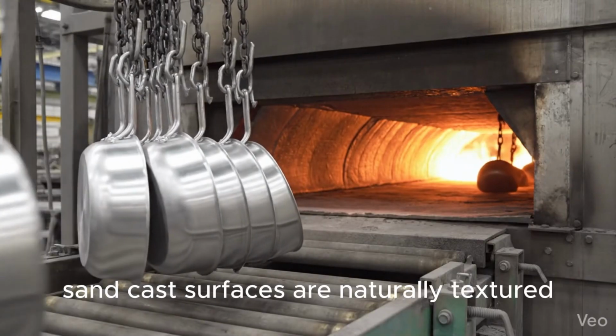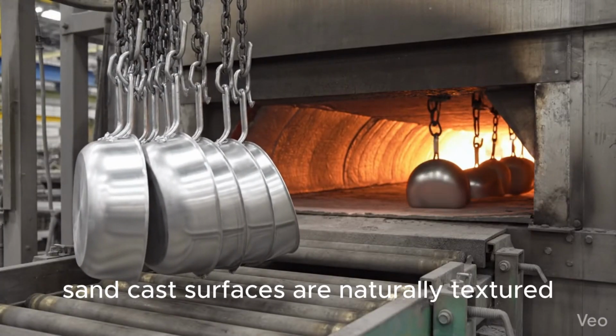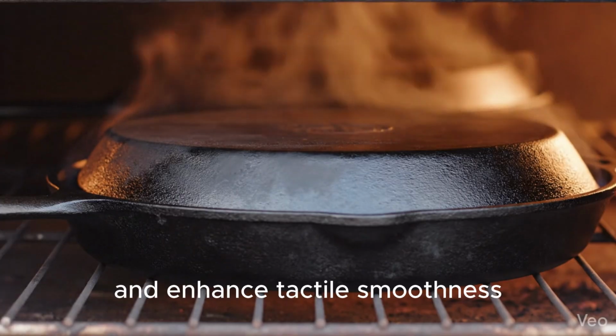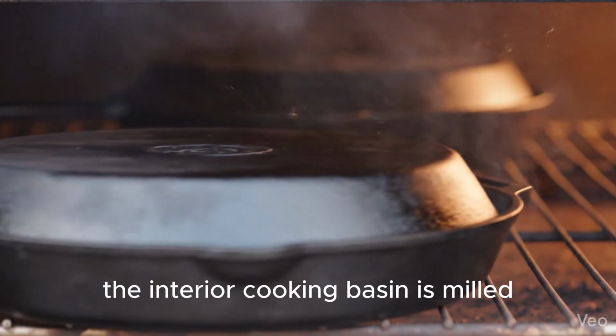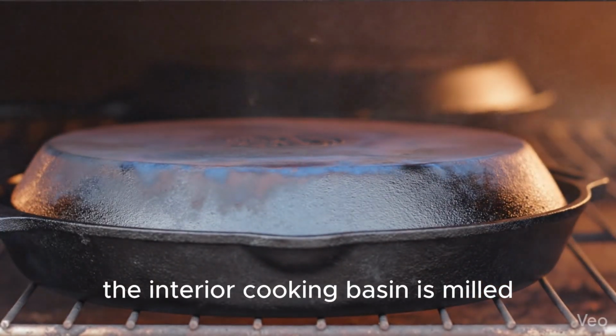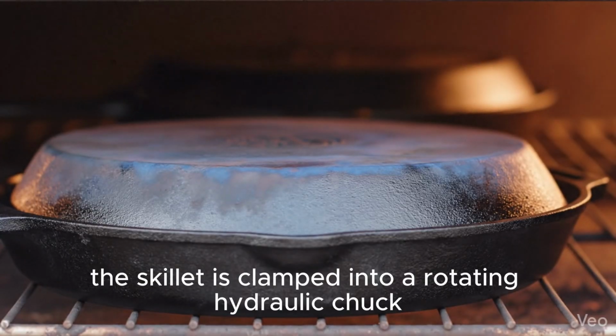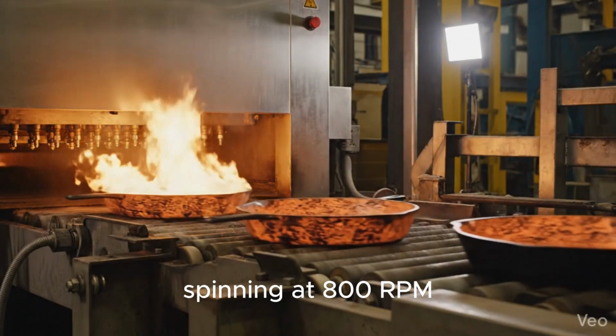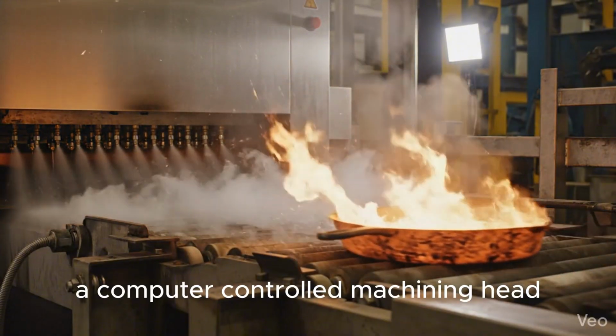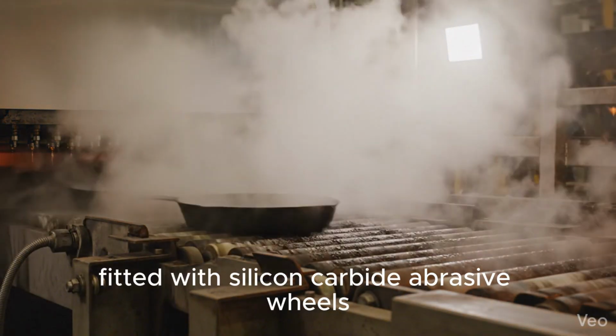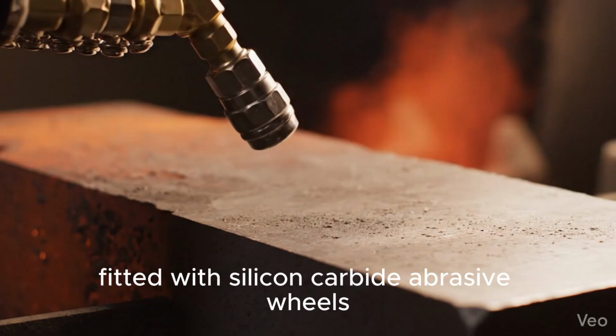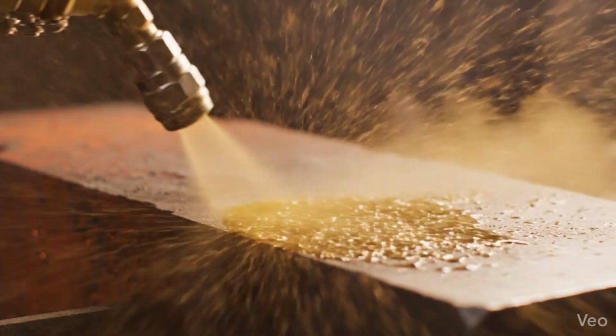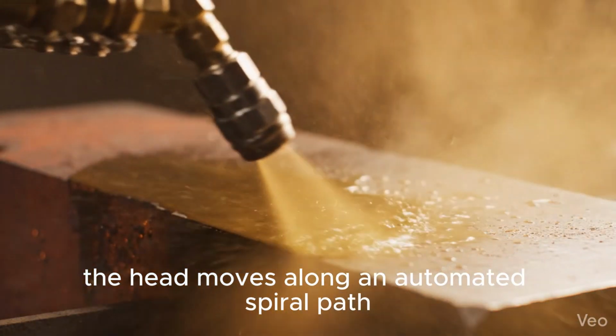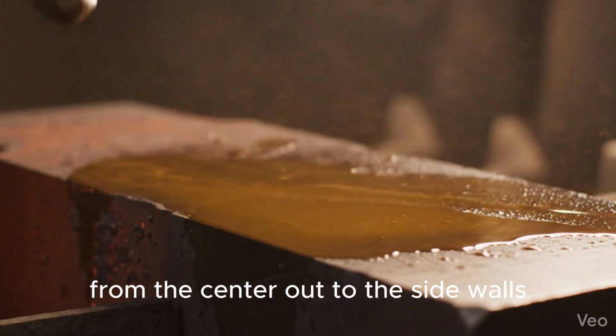Raw sand cast surfaces are naturally textured, so the surface is machined to improve the culinary performance and enhance tactile smoothness. The interior cooking basin is milled. The skillet is clamped into a rotating hydraulic chuck spinning at 800 RPM. A computer-controlled machining head fitted with silicon carbide abrasive wheels descends into the basin. The head moves along an automated spiral path from the center out to the sidewalls.